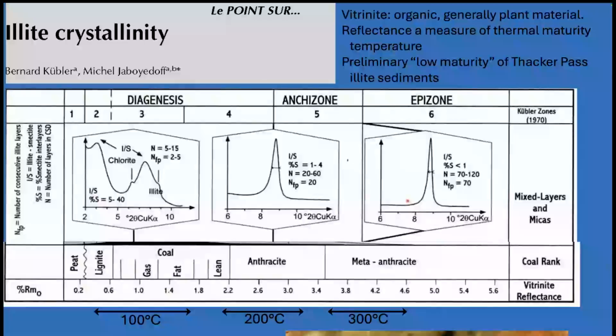If we back up, I plotted here sort of a best interpretation of diagenesis zones going into a transitional zone into low-grade metamorphism, and sort of interpreted temperatures. And different people sort of argue about what these temperatures are, but we're seeing low temperatures for diagenesis, mostly less than 100 degrees C, but in some cases in higher grades of diagenesis, somewhat higher. Whereas when you're getting up into, and notice the tighter illite peak, 200 and even 300 degrees C, once we get into low-grade metamorphism.